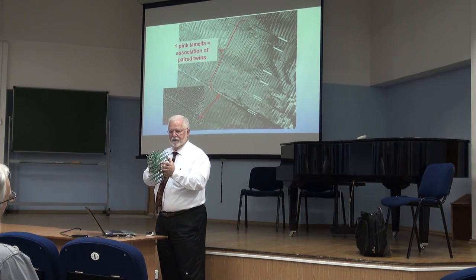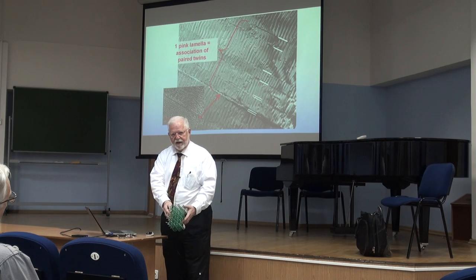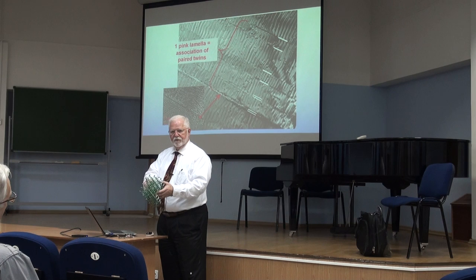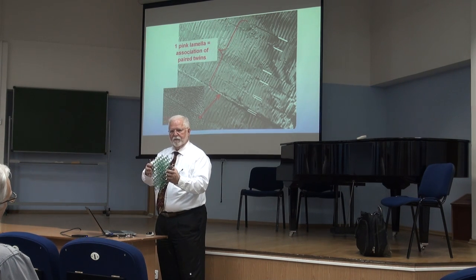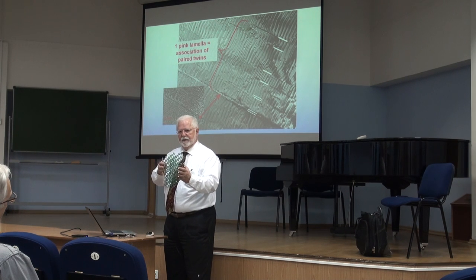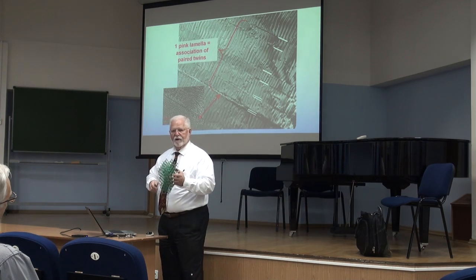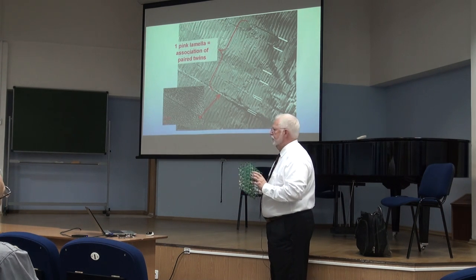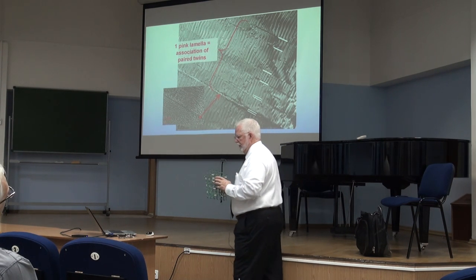Many defects. But then the diamond still sat down there for another billion years at a temperature and pressure that stabilizes diamond, and those carbons in the amorphous region slowly rebonded. The way it minimizes its energy and stress is to form parallel twin planes. This is well known in material science.